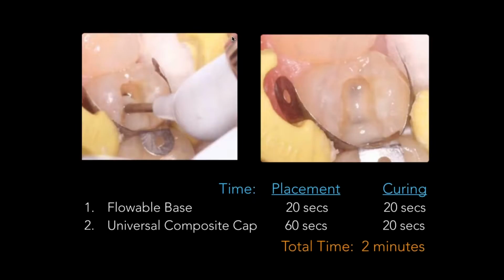Here's an example here of a low viscosity bulk fill. You can see here the access of the unit dose that I'm placing here and how this material flows. When you're working with these materials, it's really nice to place this down into the depth of the proximal box. You can go ahead and start to express this, and it starts to flow and adapt and flow very nicely and mound up. You don't need to swirl it around or really coat. If you can just kind of express it, it starts to place and starts to flow nicely.